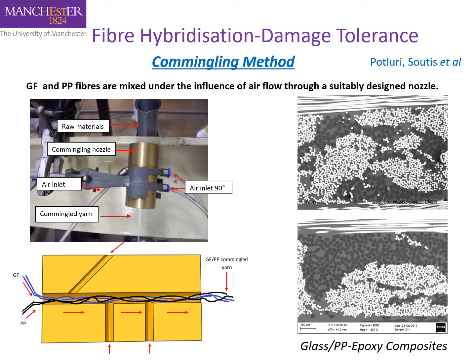Hybridization at the fiber level can also improve the damage resistance and also damage tolerance of the laminate. Glass fibers can be protected with polypropylene fibers and prevent early fiber breakage. So in this case, the glass fibers provide the stiffness and strength in our laminate, while the polypropylene fiber provides resistance to an impact event.